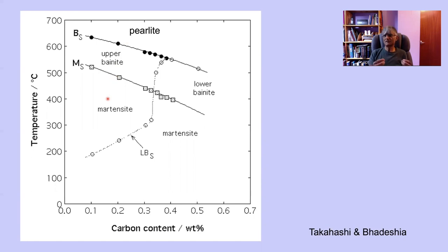carbon can escape rapidly into the remaining austenite. So for low carbon concentrations, less than about 0.4 weight percent in iron carbon alloys, you will not actually get a lower bainitic microstructure. And with high carbon steels, the prediction is that you'd go from pearlite during isothermal transformation to lower bainite and then martensite, but no upper bainite. And there is a very narrow region here of concentrations where you get all four: pearlite, upper bainite, lower bainite,